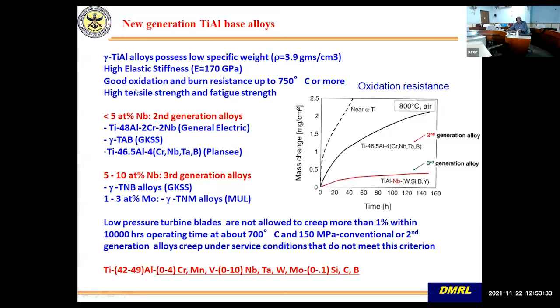And it has got very good oxidation resistance, high tensile strength, and fatigue strength. And here I'm comparing the oxidation resistance. There are different generations of gamma aluminides now. 4822, that is 48Al-2Cr-2Nb, is a General Electric GE composition. It is very famous because GE has fitted it in the flying engine and it is flying. Then there is GKSS, again a German company, and then there are Plansee compositions, and the classification is based on niobium. If it is less than 5 atom percent, then it is second generation, higher, up to 10 atom percent, third generation, and so on.